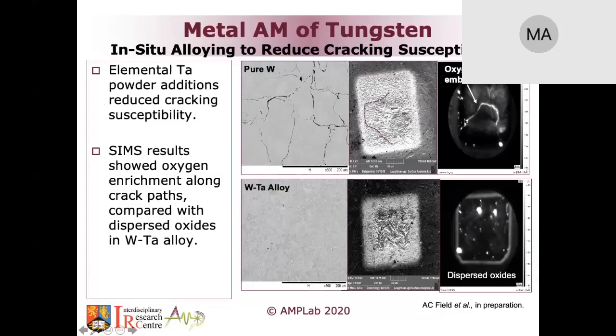SIMS showed that when you map the grain boundary, we found that it was oxygen enriched. The white line there is an indication of oxygen enrichment. So it does prove the point that the oxygen enrichment happened on the boundaries that eventually led to the cracks forming. Whereas when we looked into the tungsten tantalum, obviously you don't see cracks. You see some dispersed oxides. The slightly bigger spheres are porosity from the additive manufacturing process, but the tiny small ones are dispersed oxides.